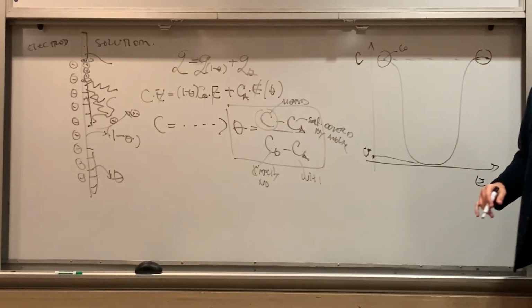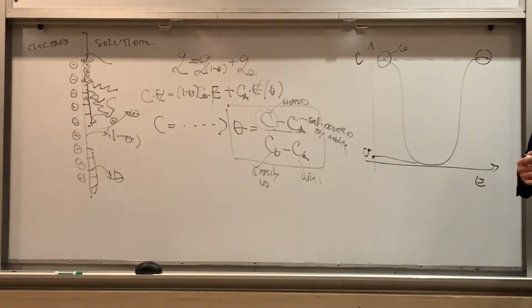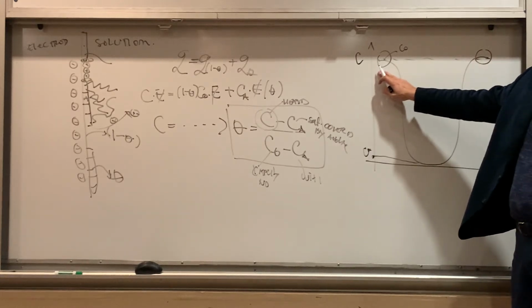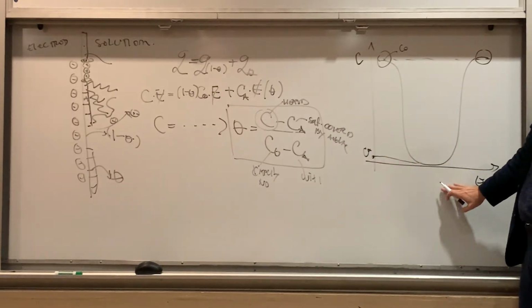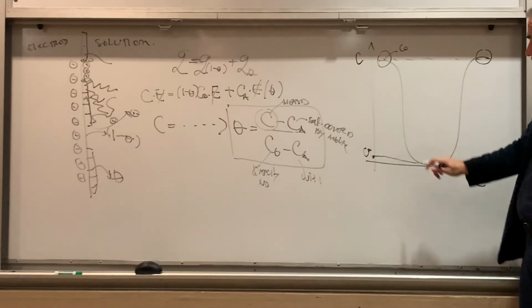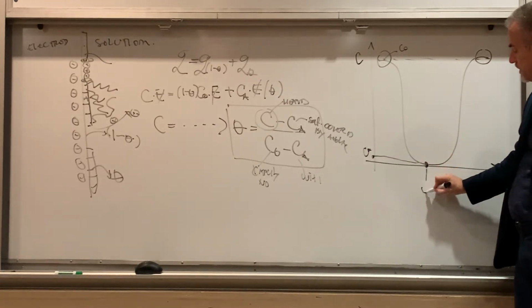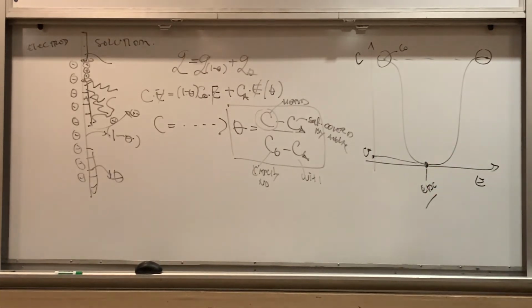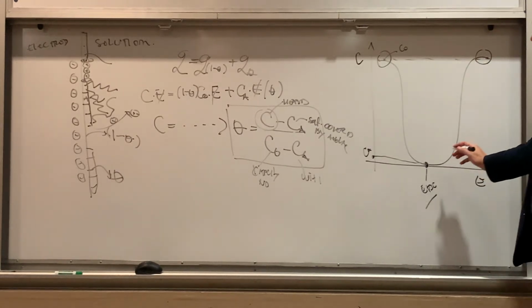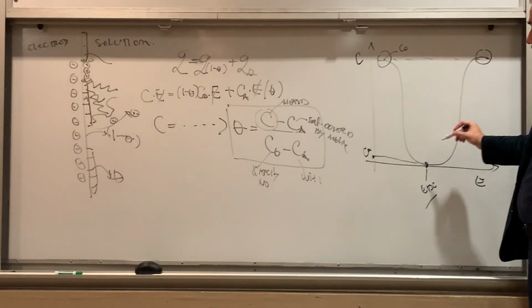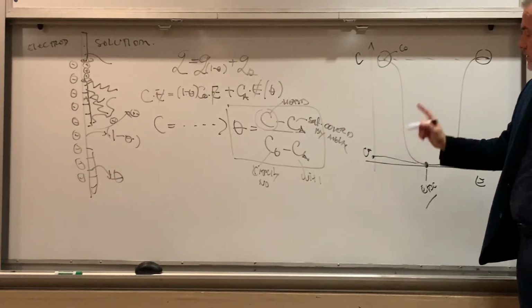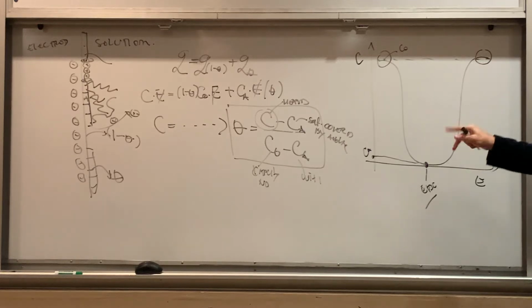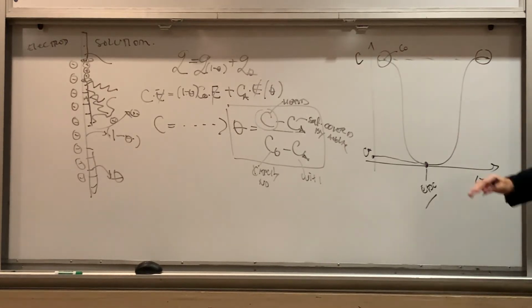Okay. So what we really do when we study adsorption of the additives on the surface is we study capacitance of the double layer as a function of the potential, and we see something like this. Here, obviously, somewhere will be EPZC, because the organic additives, as I'm going to explain in a moment, always adsorb within the region of the PZC. And then as you move away, the coverage has some dependence on the potential, which we don't have to explain right now, but the bottom line is this.